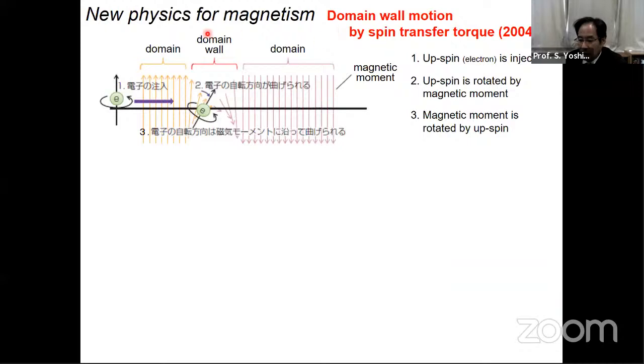In 2004, new physics for magnetism was demonstrated: domain wall motion by spin transfer torque. This one is an electron with up spin, and these arrows are magnetic moments. In this domain the magnetization is upward, in this one the magnetization direction is downward, and this position is a domain wall.